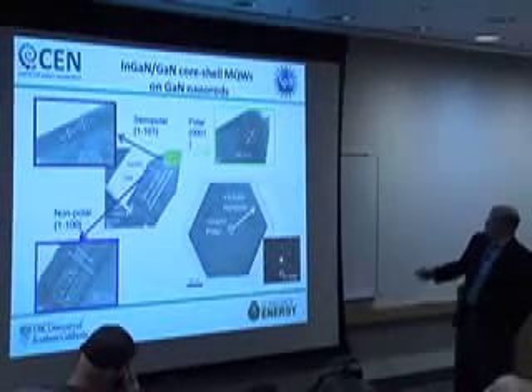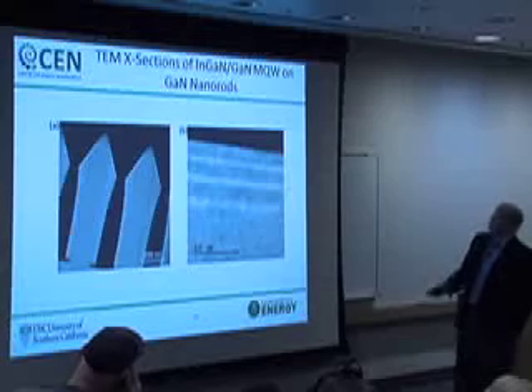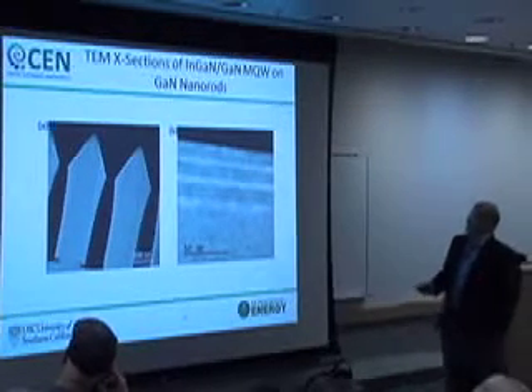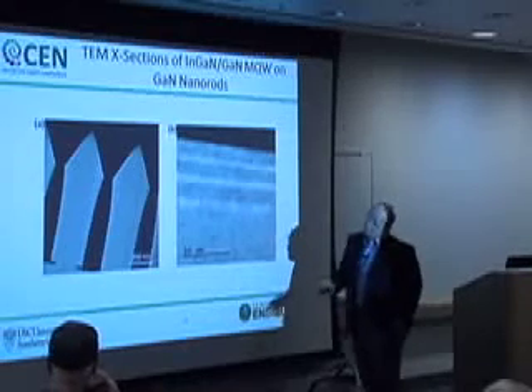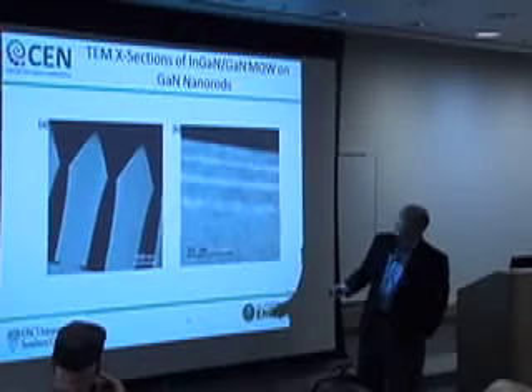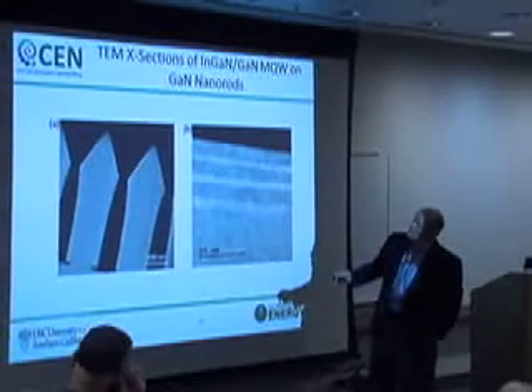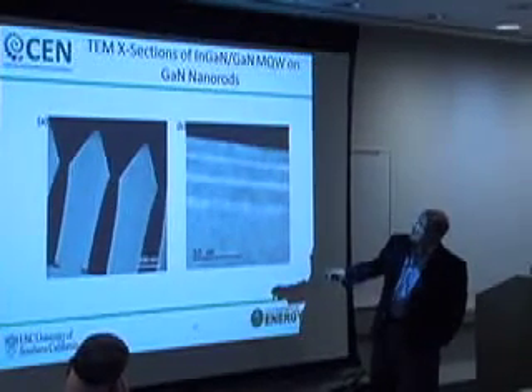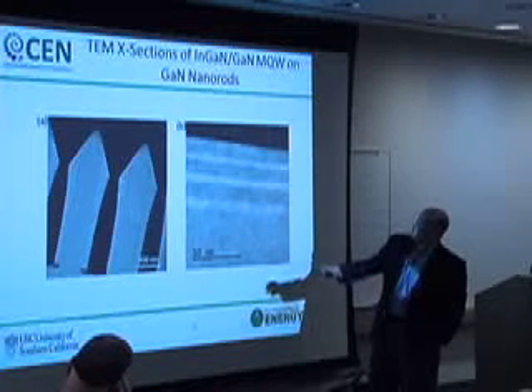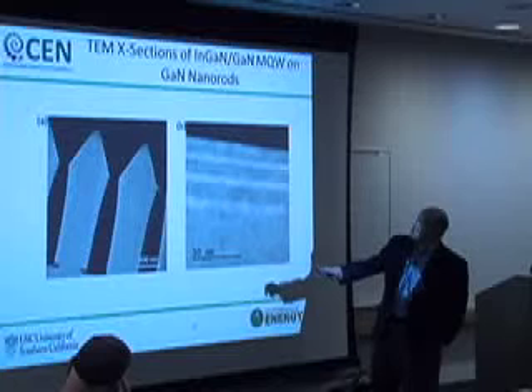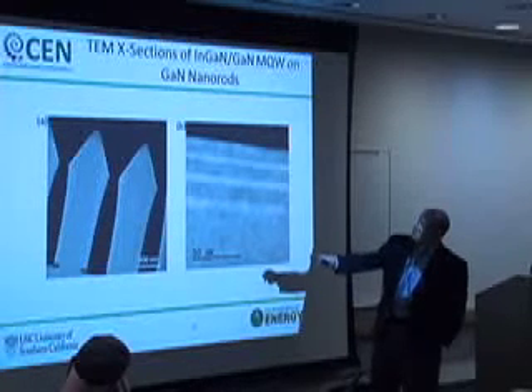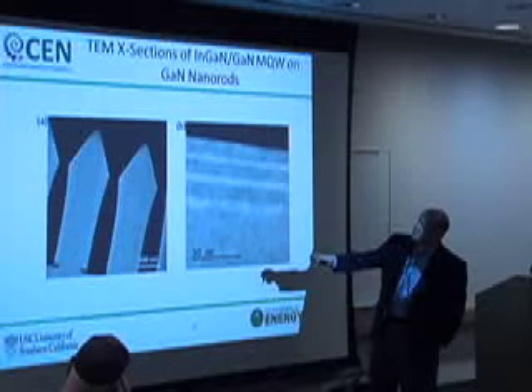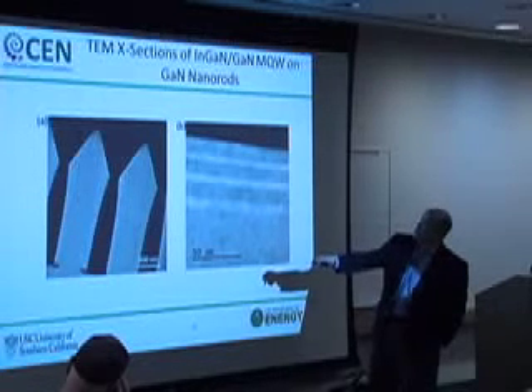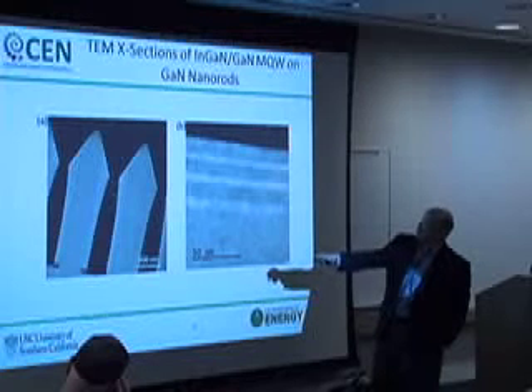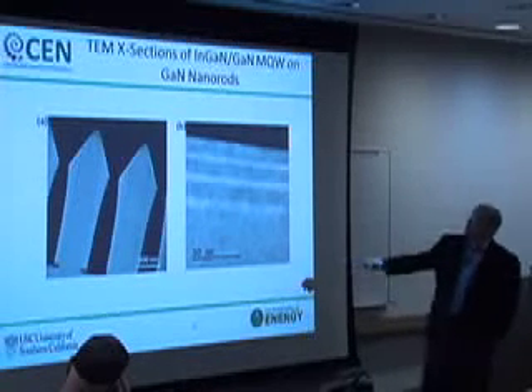This just shows a cross-sectional TEM, and you can see that the quantum wells are continuous and fairly uniform around the structure. This is another image taken from a structure we grew later in our development, and it shows the quantum wells and how the growth changes in the vicinity of the intersection of these planes. We believe that because the growth rate is so slow here, reagents land on this surface, diffuse down to this region, and so we get thicker growth in the collar around the two regions, but still have very thin quantum wells up here.